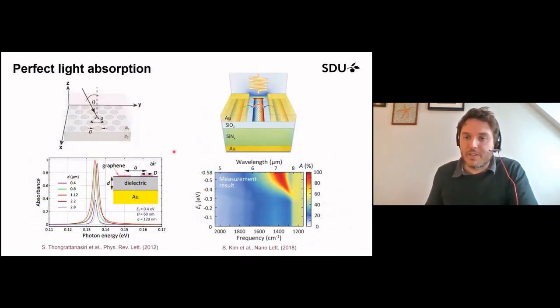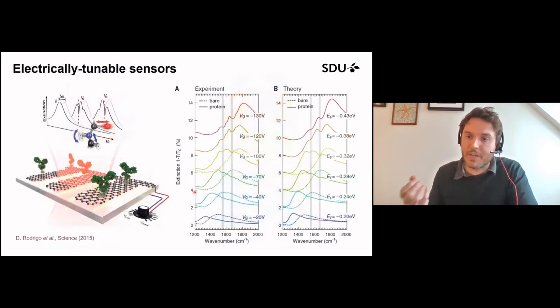So by changing the Fermi energy, you can actively tune the plasmon resonances to different wavelengths and change the absorption. This has been demonstrated in a number of experiments. There have been some reports of actually achieving perfect light absorption in graphene nanoresonators arranged in a periodic way. This was just a theoretical prediction up until a few years ago, and then it was experimentally demonstrated using ribbons of graphene combined with ribbons of gold, right? And you can see they can achieve 100% absorption at a specific frequency that depends also on the Fermi energy. So this is already quite amazing because it's just a single atom layer thick of carbon, and it's absorbing 100% of the light.